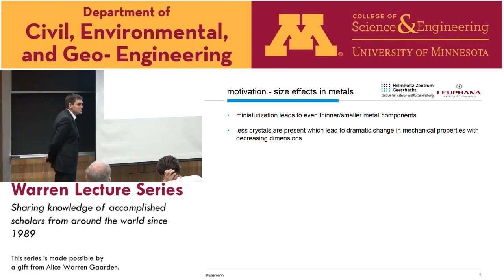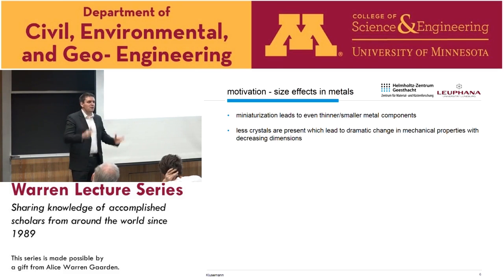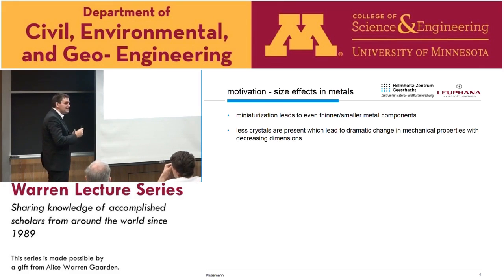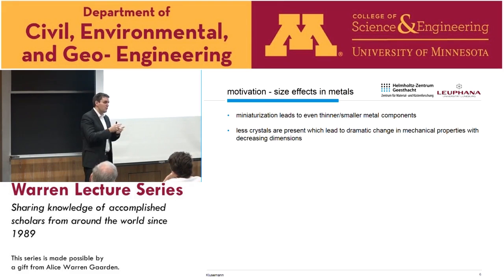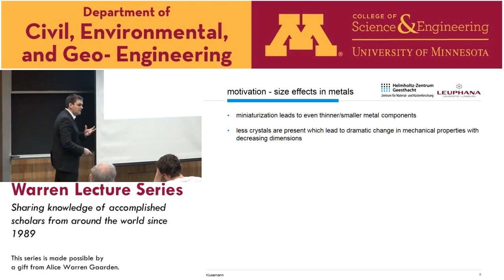Okay, so the first topic I will talk about is related to size effects. And size effects, when you think about that, you classically think about a Hall-Petch effect. However, this is not what I'm talking about today. So just imagine the following case. You have the classical miniaturization, which leads to even thinner and smaller metal components. But this doesn't mean that your grain size has also to be decreasing. Of course, if you're talking about nanocrystals, this is true. However, in general, this has not to be the case. It just can be the case that your specimen size is decreasing. And if you have this case, then of course you have much less crystals present, and this leads to a dramatic change in your mechanical properties.